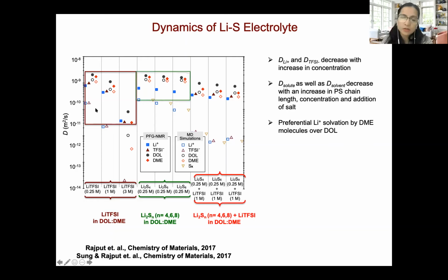The second factor we looked at is the polysulfide chain length. And we found that as we increase the polysulfide chain length, there's a slight decrease in the diffusion of all the ionic species as well as solvents. And finally, when we add salt to the lithium polysulfide species, there's a further decrease in mobility of ions in the solution. We found a very interesting trend here for all the systems that we considered. And we noticed that for every system, the diffusion of the DOL solvent is higher than DME solvent.